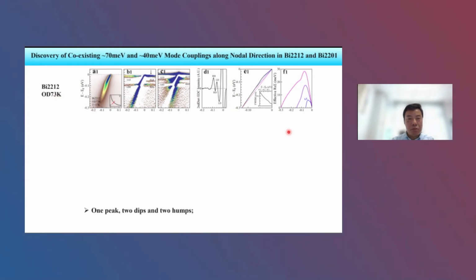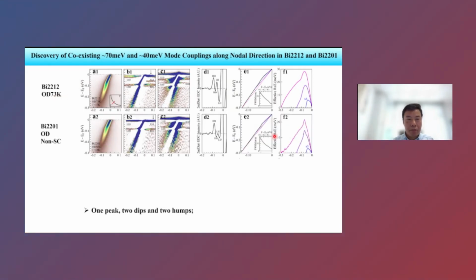If you go to Bi2201, heavily overdoped, not superconducting, you measure the real, original data, you do a second derivative, you can also see two flat bands. That means two mode couplings here. And you can also do a simulation.